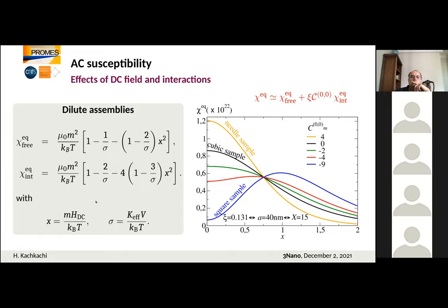X is just the DC field, and sigma is the well-known effective energy barrier. If we plot the total susceptibility, we see that it depends very strongly on the shape of the sample. Here, we're talking about a sample that is an assembly of nanoparticles embedded in some matrix, solid or liquid. For a solid matrix, you can have the sample in the form of a square or a needle, which is a really prolate system. This is the equilibrium susceptibility as a function of the applied field for different shapes. We can go from a bell-like shape to some monotonic behavior.